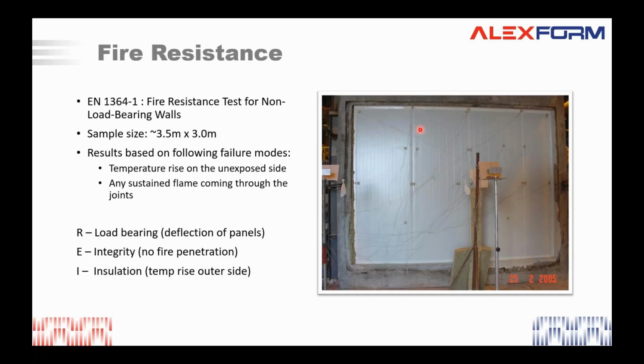3-meter long panels on this opening, aperture, and behind here is a furnace. And inside is real hell. And I've seen it with my own eyes. Inside it becomes a pure inferno ablaze. So you have up to 850 degrees Celsius inside. So this is a fully developed fire. What you want to see during this test is on the outer side, the face you're looking at now, the temperature should not rise above a certain level.